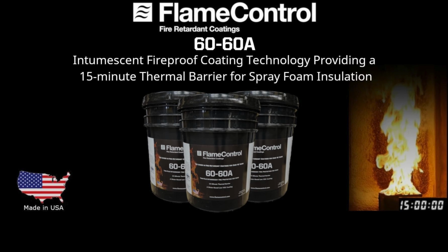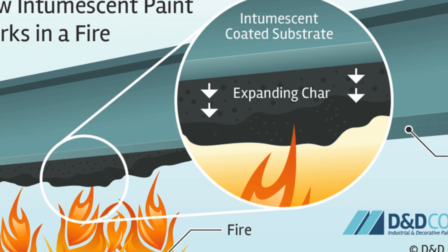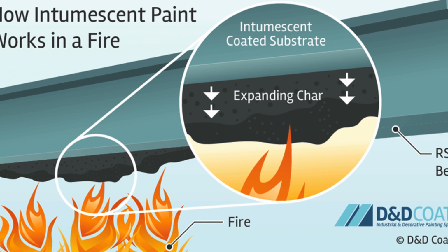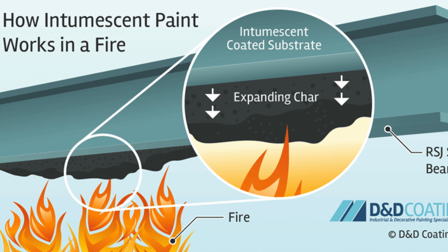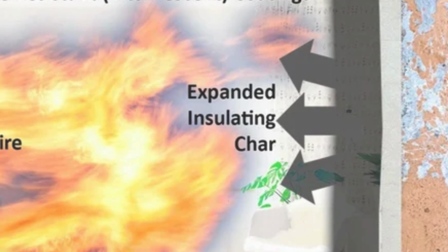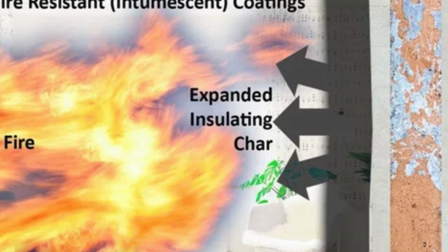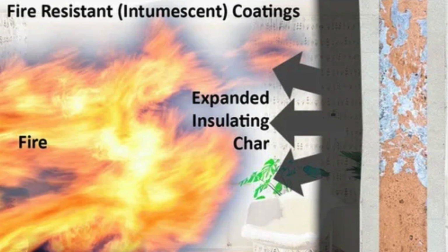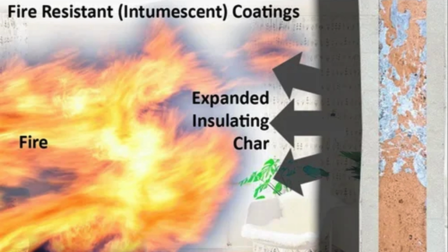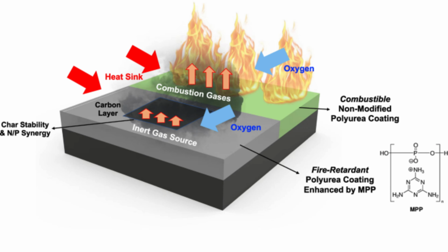When heated, 200 to 400 degrees Celsius, the coating undergoes a chemical transformation. Acid source, for example, ammonium polyphosphate, APP, decomposes to form phosphoric acid. Carbon source, for example, pentaerythritol, starch, lignin, is dehydrated by the acid, forming a stable char. Blowing agent, for example, melamine, urea, expandable graphite, releases gases, nitrogen, ammonia, carbon dioxide, that cause the char to swell, foam into an insulating layer.